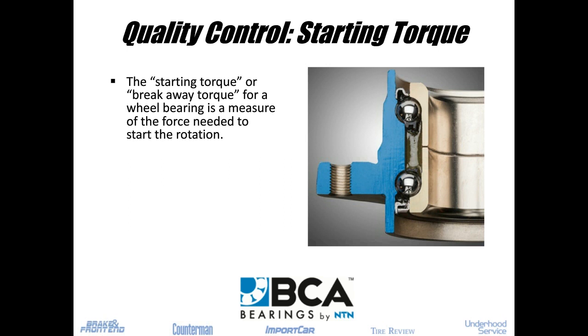It's called starting torque or breakaway torque. And this is where they measure the force required to get the bearing moving and starting the rotation. So this test is very involved. It's not just pulling the bearing offline and then measuring it that way. There are steps to make sure, moving it back and forth 10 times in a certain direction, a certain amount of degrees, to make sure that the results are accurate and repeatable. So this is what they're checking inside.